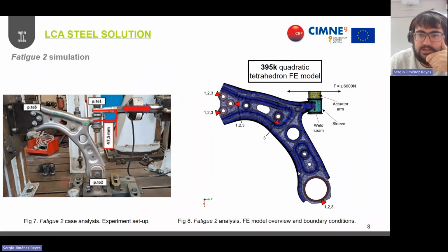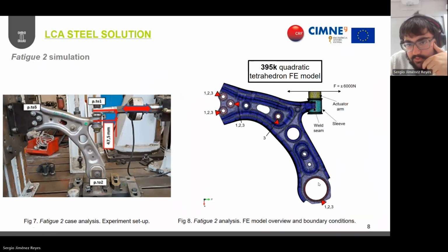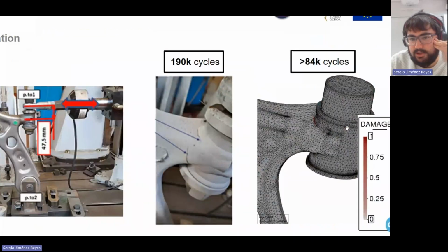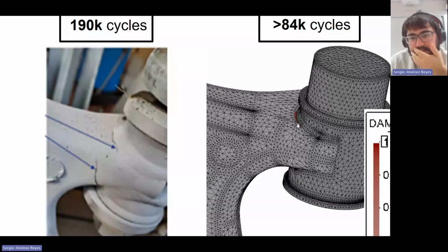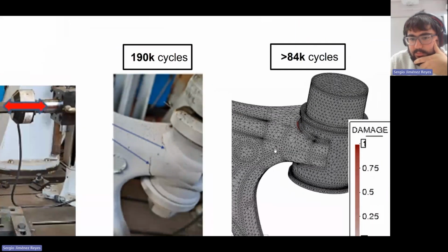And then going towards this second scenario, where we are focusing on the weld area, these are the new boundary conditions that we applied in our model, fixing these two ends here and this inner region, and we applied the force here. So we have the weld seam in this connection region here. Basically, this is the type of result that we obtain. Let me just zoom in to better see the progression in the crack path. So we have, first of all, this initial damage area, which matches with this region identified experimentally. And then at some point, it also starts to propagate the crack in this bottom region.